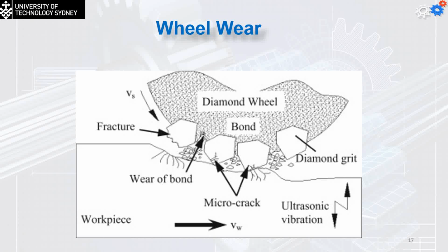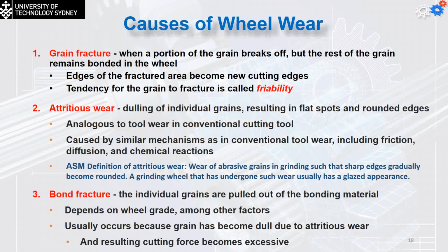Why do we have the wheel wear? First, because the grain fractures, as we saw in the previous diagram. As the edge fractures, the area becomes new cutting edges, and the tendency for the grain to fracture is called friability, as we mentioned, and we need this friability to happen. We have some attritious wear, which is dulling of the individual grains, resulting in flat spots and rounded edges. And this is a very unwanted process.